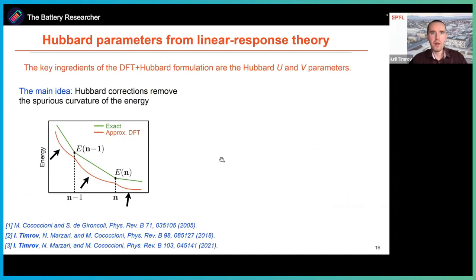Now, as I mentioned before, in those corrective terms, we need to know somehow those parameters, on-site U and intersite V. They are not known a priori. So what people do, the simplest solution, is simply to tune or calibrate them until you reproduce some experimental property of interest. For example, band gap or magnetic moment or lattice parameters or oxidation enthalpies, you name it. However, this is not an ab initio approach, because you sort of tune it somehow, but it would be really nice to have some way to determine these parameters from first principles. So if I give you a system, you can simply compute those parameters without relying on experimental results, because sometimes we don't have experimental results. Then we don't know how to determine Hubbard parameters, but if we can compute them, that's much more robust.